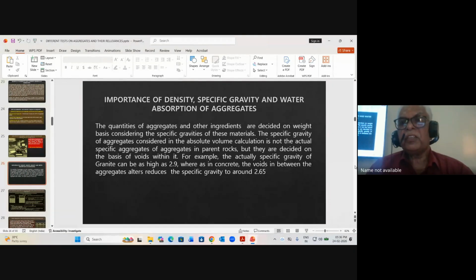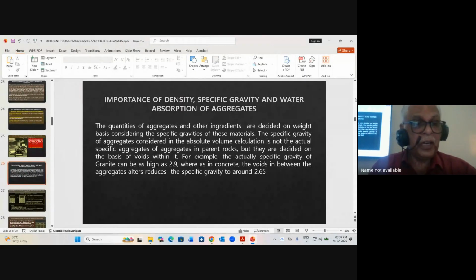If you take a natural aggregate, suppose granite, geologically its specific gravity is about 2.9. But we do not consider 2.9 for design mix, because we are considering the voids within the aggregates. That's why a specific gravity of about 2.65 to 2.7 is normally used for granite aggregates in design mix, even though 2.9 is the actual specific gravity from a geological point of view. For design mix purposes, where we have to consider the voids also in between the aggregate, we consider specific gravity of around 2.65.